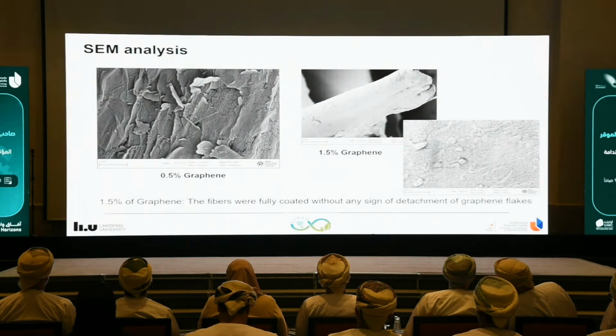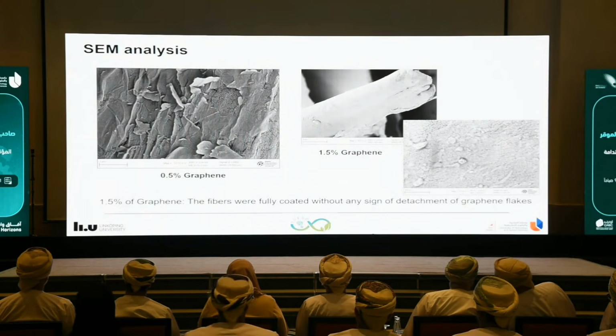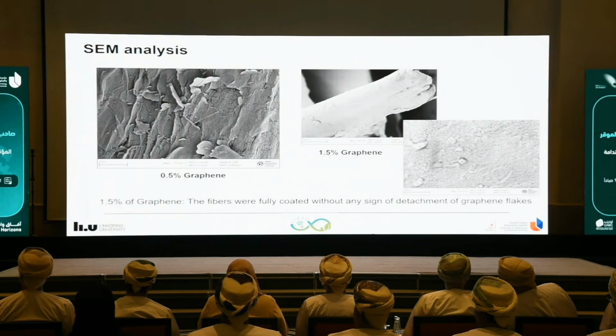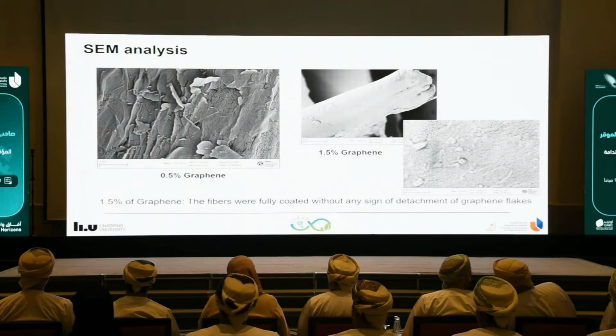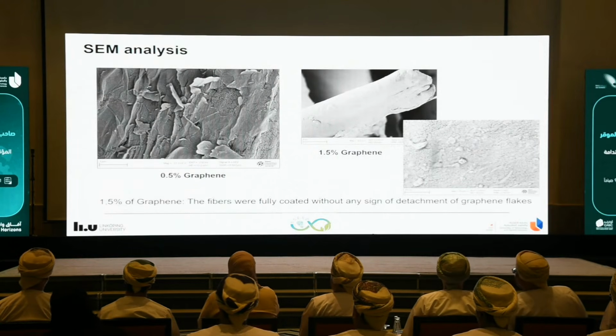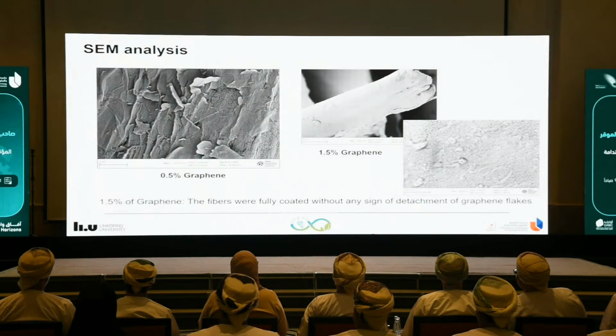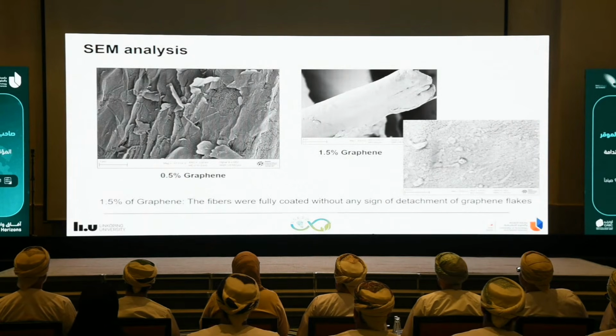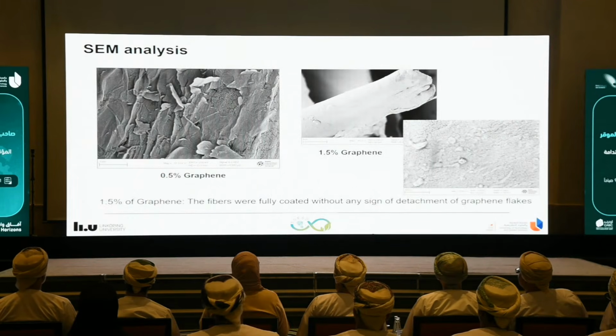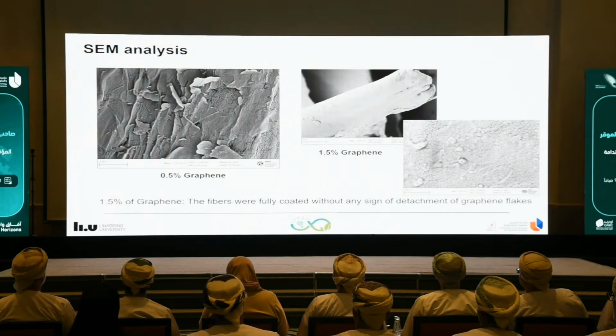We also did some SEM, scanning electron microscope analysis, to understand what is happening at the microscale level. Why we didn't get good results at 0.5% concentration. And it showed that when we did the coating with this concentration, the graphene flakes were not covering the whole area of the fibers. However, at 1.5%, the fibers were very well coated, and the graphene was covering the whole areas.